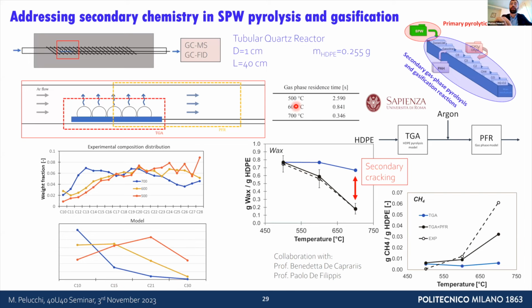What Riccardo did is design a reactor where a layer of polymer is added on a little boat, and by moving this boat into the flow reactor, he was able to adjust the residence time. At different temperatures you have different residence times, and he measured and characterized the experimental wax composition and the gas phase species production.